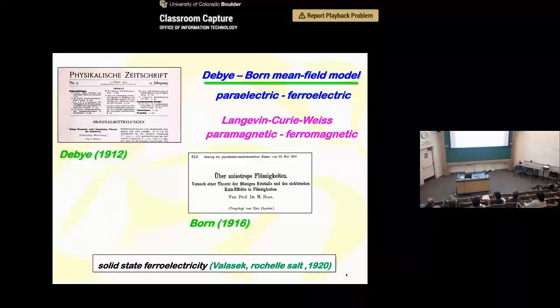And this model is sort of drawn from the Langevin-Curie-Weiss model for the paramagnetic to ferromagnetic transition, this mean field model. They basically sort of went in the same direction, exchanging electricity for magnetism, so to speak. A sidelight is that at this time, solid state ferroelectricity wasn't discovered until 1920. So these papers are effectively predictive, especially this one, of the finding of ferroelectricity in solids. And actually, this model is very applicable to solid state ferroelectrics.